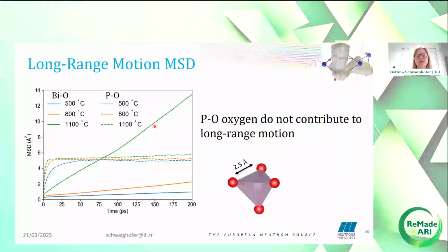For BPO, the mean square displacements look very different. At all temperatures, the MSD curves for the oxygens in the phosphorus oxygen sublattice plateau at around 5 angstrom squared, which shows that the oxygens around the phosphorus centers do not contribute to long-range diffusion, and all long-range diffusion in BPO is caused by oxygens in the bismuth oxygen sublattice.